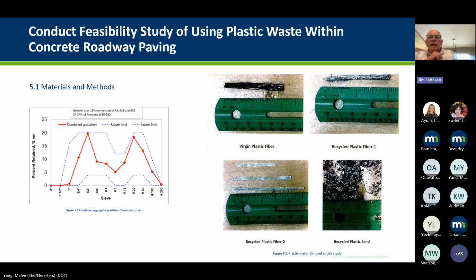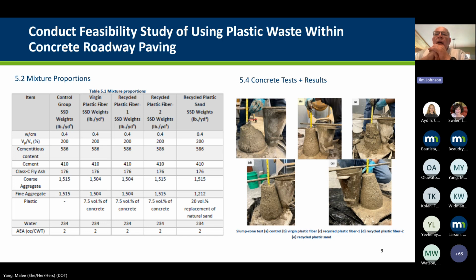Next slide, please, Haley. And again here, we wanted to show on the left the mix proportions, again following MnDOT design standards. As you see, the leftmost column of the five is the control group with just virgin aggregates. And then as you go to the right, utilizing each of those four different fibers or sands that we talked about on the previous slide. On the right, one of the first tests performed was, of course, on slump. You'll see a visual picture of that, utilizing each of those five mixes, from the upper left being the control group, and then going across, down, and across again for the other four that incorporate the plastics, either as fiber or as sand.